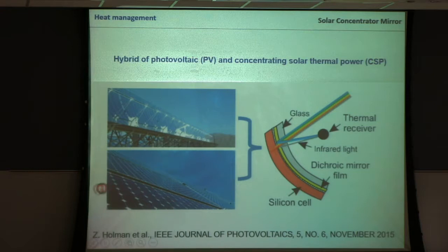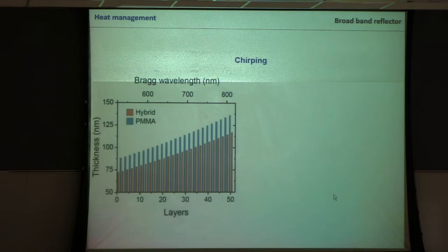So this is work by Zach Holman. He uses commercially available infrared mirror foils from 3M, but I have to say they have a disadvantage in that they are made with a polystyrene PMMA derivative, so they have a very, very small reflection band in the near infrared. In case you want to really have heat mirror management, you want to have a very broad reflection band. And I see my time is possibly starting to run out.